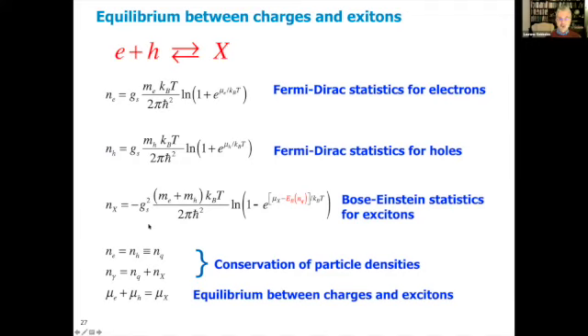Excitons behave like bosons, so there you get Bose-Einstein statistics, so you have a minus sign here instead of this plus sign, and you have here the exciton binding energy that is subtracted from the chemical potential of the excitons. And then there is conservation of particle density, so the number of electrons and number of holes are equal, and that is equal to the number of charges in the system, and then the number of absorbed photons is equal to the number of charges plus the number of excitons. And in equilibrium, the sum of the electron and hole chemical potentials should be equal to the chemical potential of the excitons.